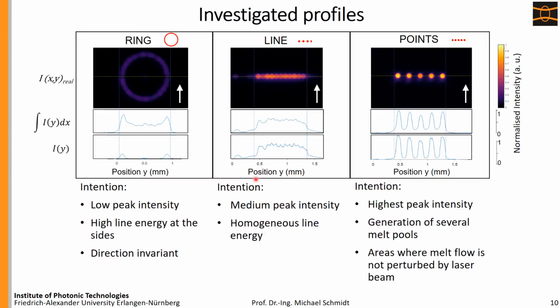So some of the first beam shapes we tried was the ring shape, as you can see here. You can see here the intensity. A line shape, which is connected dots, and a point line, which is non-connected dots, to allow an area always between the 2 points that is not influenced by the laser beam. So you can see here we have quite a low peak intensity, as you can see also from the light violet color, whereas here on the right side we have the highest peak intensity, which makes this beam shape prone to material vaporization.